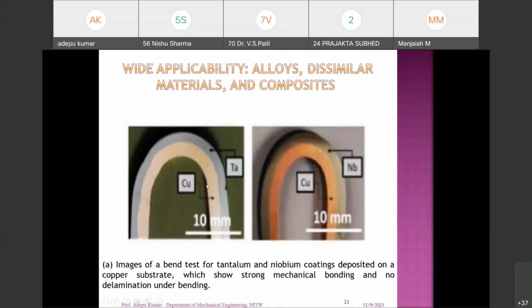They have made copper to tantalum, copper to niobium. You can see the physical properties of copper, tantalum and niobium. There is a very large difference in melting point temperature, even though you are able to successfully weld it through these techniques. So this is very useful for industrial applications. During welding or melting processes, it's impossible to get these kinds of combinations. With this technology only, irrespective of the difference in melting point temperature, you can successfully complete this job.